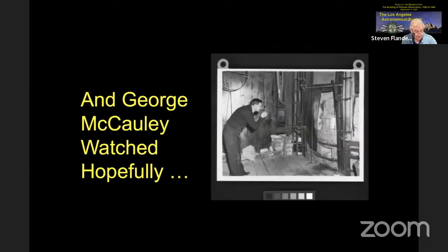Well, starting at about 7 a.m., workers began scooping 2,700 degree molten glass from the melting ovens using ladles that moved on overhead tracks. Each ladle held 750 pounds of glass, and once filled, the workers rolled the ladles to the mold where the glass was poured over the ceramic plugs. Each pour was followed by a refill at the melting oven, and so the process was repeated until the plugs were covered to the depth of 6 inches or more, and the mold had reached a capacity of 20 tons. Well, Macaulay kept close watch on everything that was taking place. By late morning, the mold was filled, and as far as he or anyone else could tell, the operation appeared to have been a success.